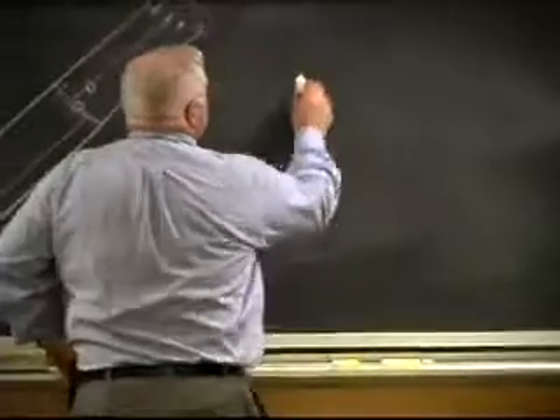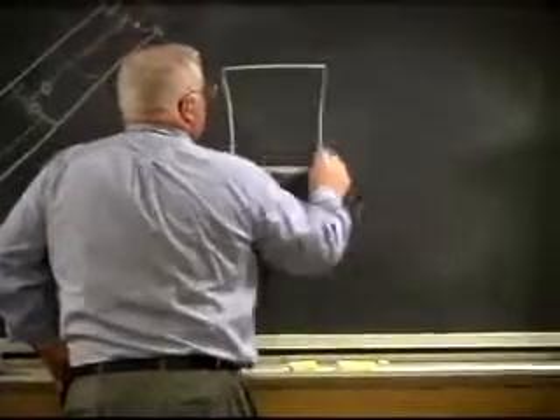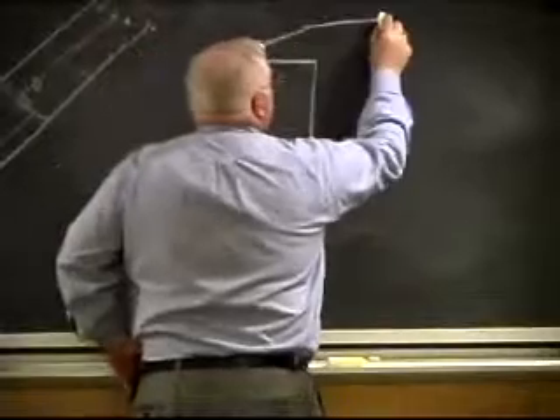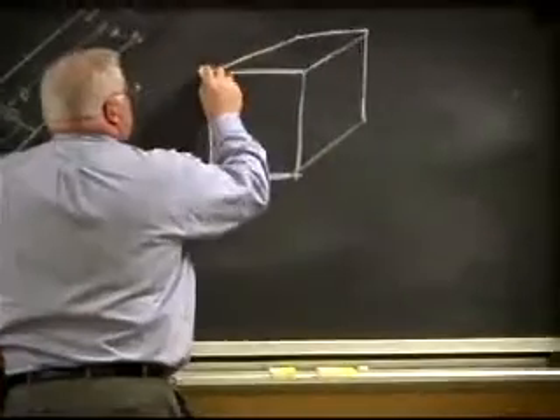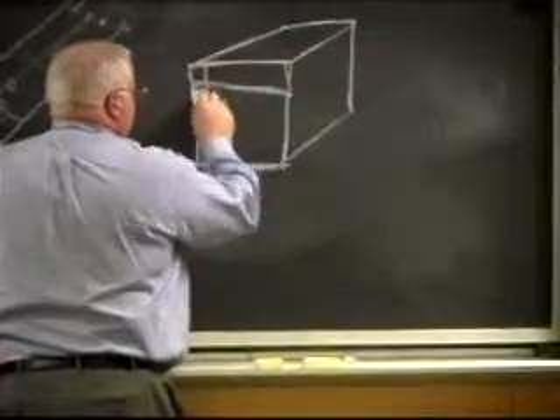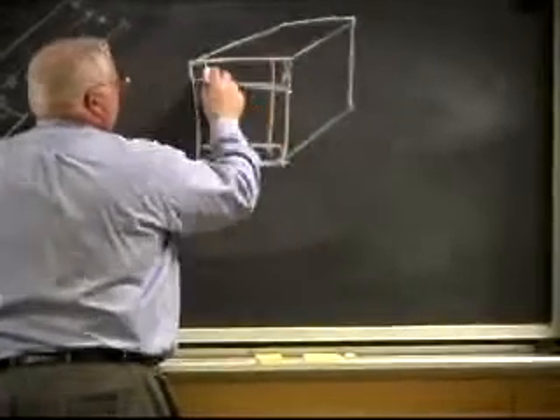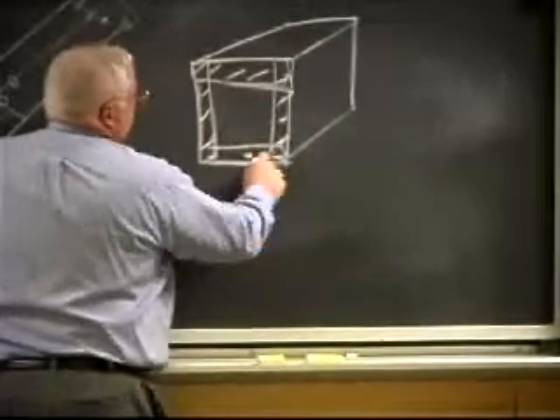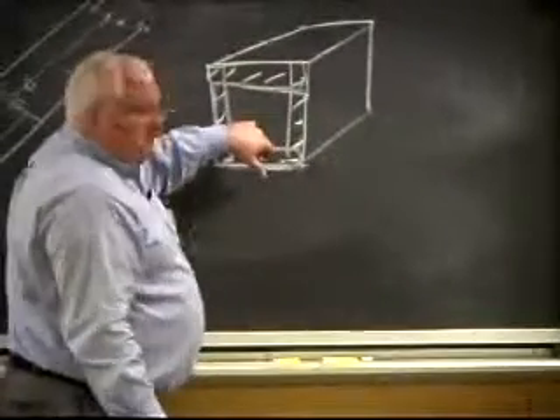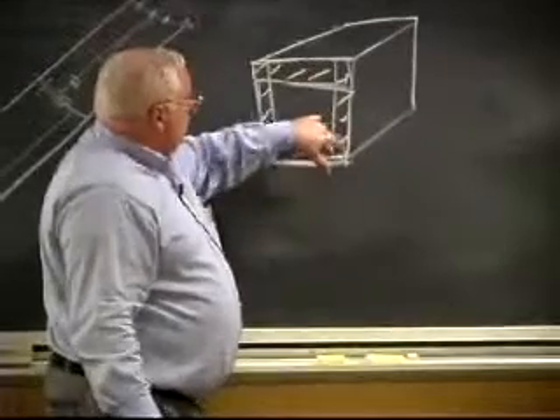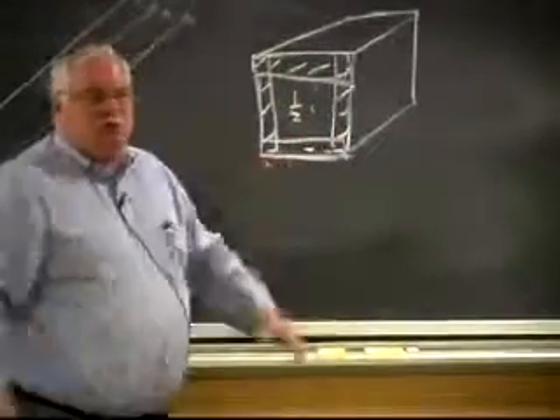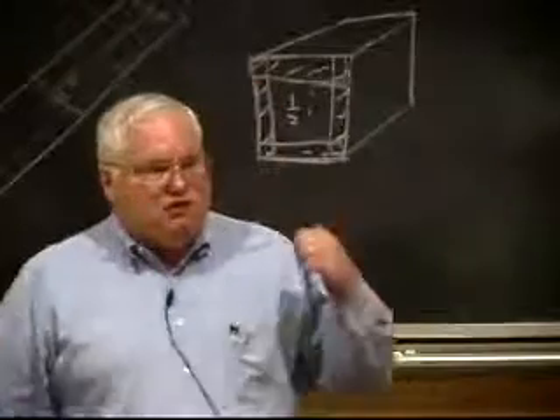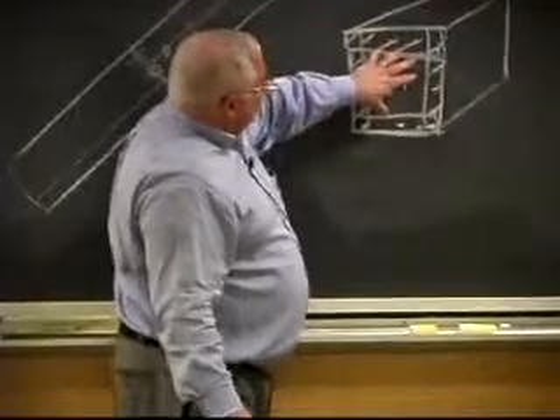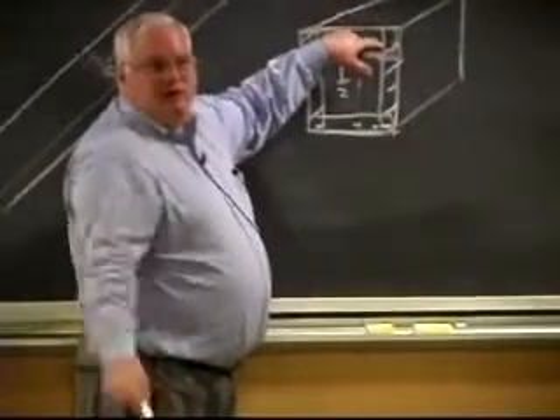I look at the drawing, and it turns out these are inch or inch and a half square solid pieces of aluminum. On the drawing, if I'm going to weld one of these to another one, they were only calling for a partial penetration weld. You had 4 welds around this thing, but the center core wasn't welded at all. This might be a 1/4 inch penetration, and I had a 1/2 inch by 1/2 inch inside this thing that wasn't welded. Well, clearly they weren't looking for full strength. Plus, they had a little more than half the area welded, but the whole thing only had half the strength in the heat affected zone anyway.